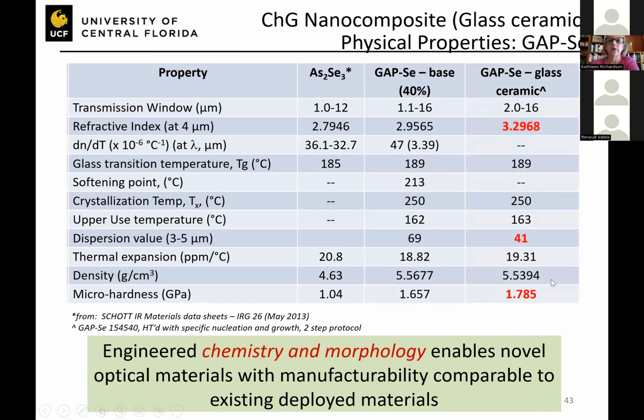And the important thing to note is not only can we change the optical properties by a lot, but we can also change the dispersion. We can change the hardness. We don't change the density very much because the constituents that are there have only changed a little bit in terms of whether they're in the disordered amorphous state versus the crystalline state. And remember, in this particular example, we're talking about between 15 and 18 volume% of crystallites, and the crystallites are all sub-100 nanometers in size. So the volume fraction is nominal, but you can see now we have a knob to tune these properties. So this is important.